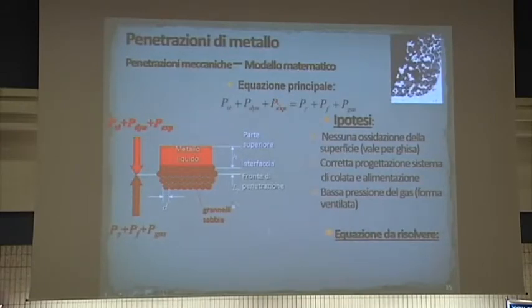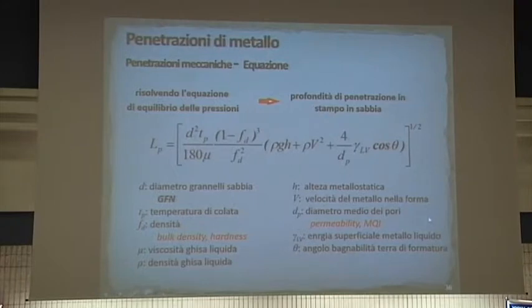In mechanical penetration, we understand this by simply a force balance. So if you look at what's trying to push the metal in: static pressure, dynamic pressure, expansion pressure. And what prevents it from going in is the capillary pressure, the most important, the friction pressure, and if you have gases from the mold, the gases coming in. And we can simplify the equation and then simply solve it as a balance between the static and dynamic pressure and the capillary and friction pressure. And I'm going to show you this equation, and that's probably the only equation. But what's interesting in this equation is that it calculates the length of penetration, how much the metal penetrates in the mold.